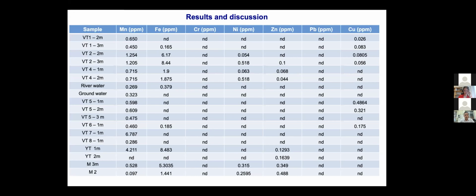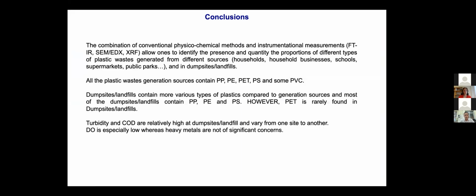There are, of course, some, linked to manganese, which is not really high. Even though it is higher than the detection limit and not close to zero, the concentrations are not that much. So we conclude that the combination of conventional physical-chemical methods and instruments for measurement by FTIR, SEM-EDX, and XRF allows us to identify and quantify the proportion of different types of plastic waste generated from different sectors, and the plastic waste collected from dump sites and landfills.